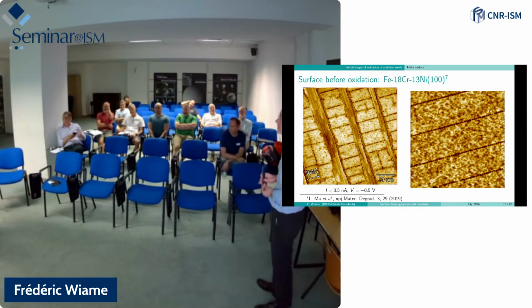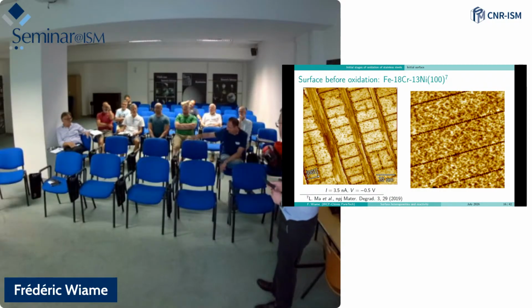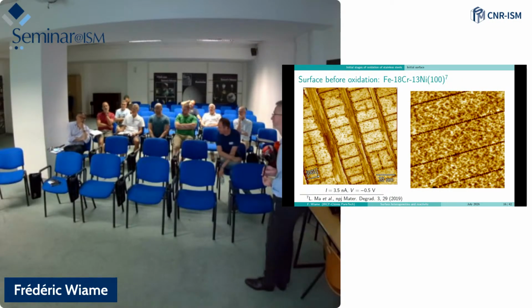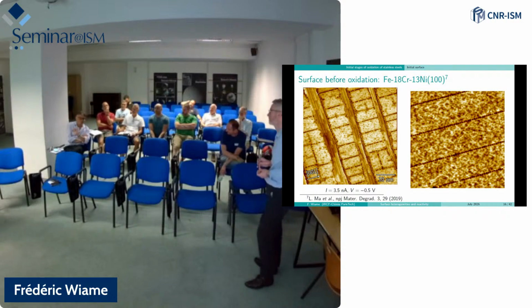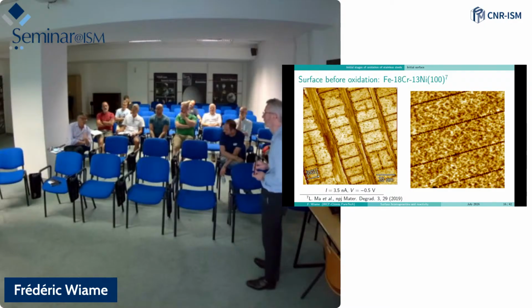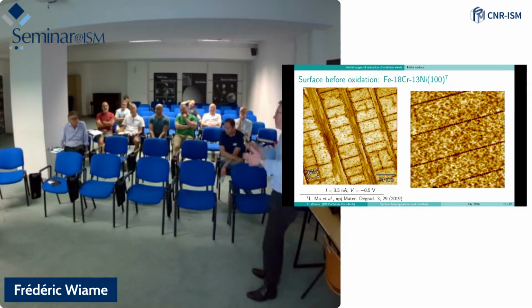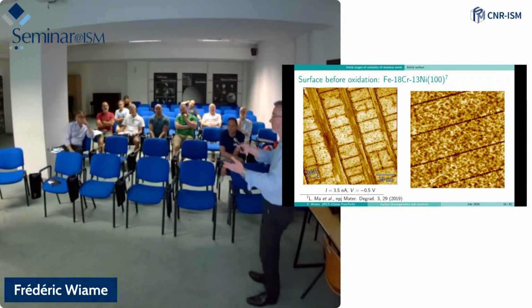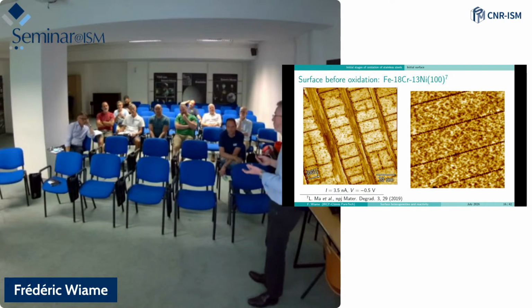Okay. So please answer. No, just a curiosity. I mean, I'm not an expert. As far as I understood, you create a native chromium oxide layer. So if you put chromium oxide from the very beginning, like ALD, for example, can you really cover it without problems? Yes, this is something which has been used for a long time in the industry. You take not even stainless steel, just normal steel, and then you deposit chromium on top of it. So this is a way to avoid corrosion.